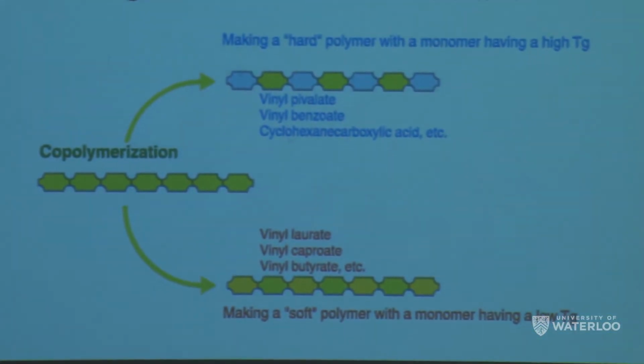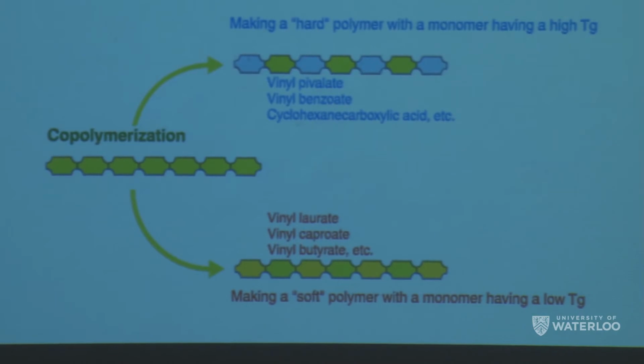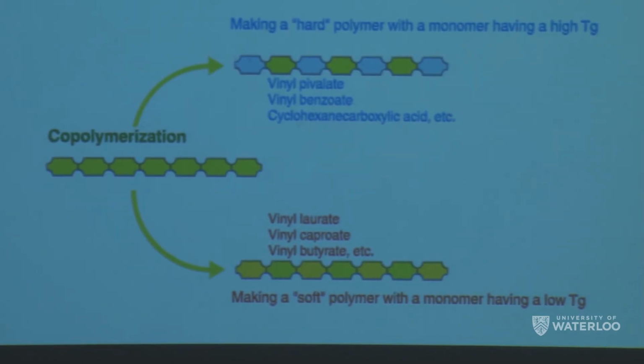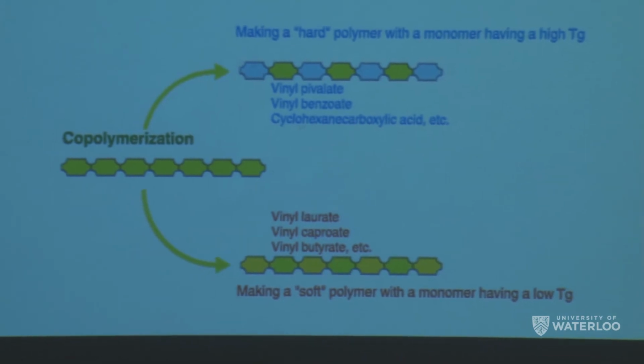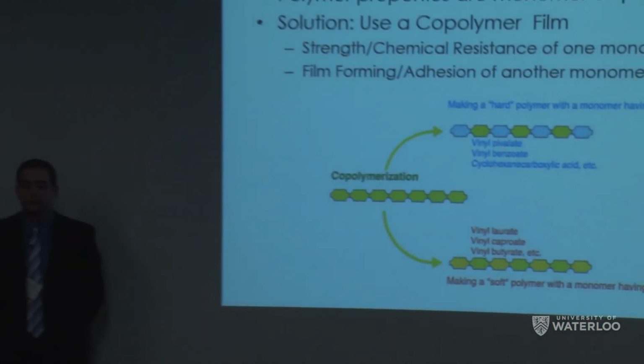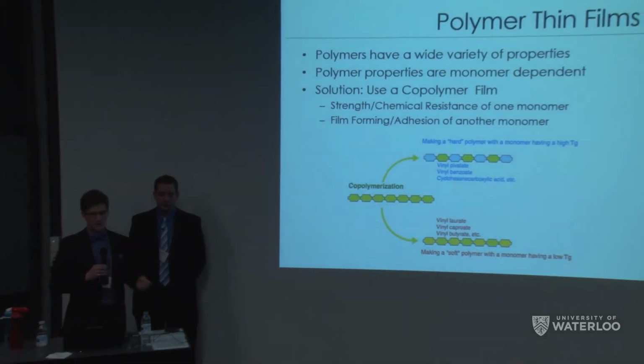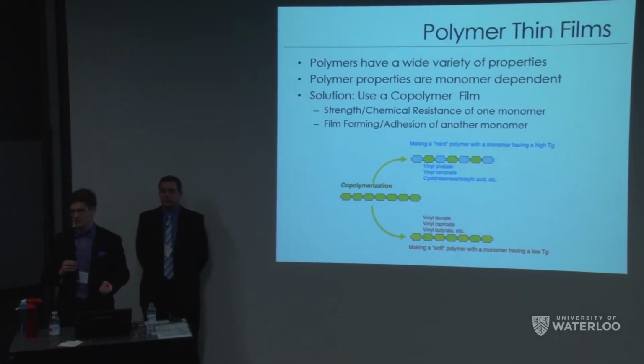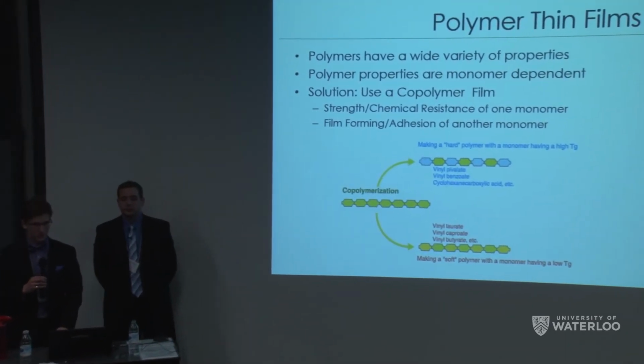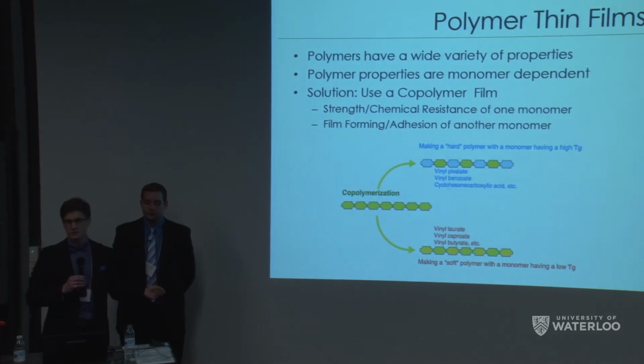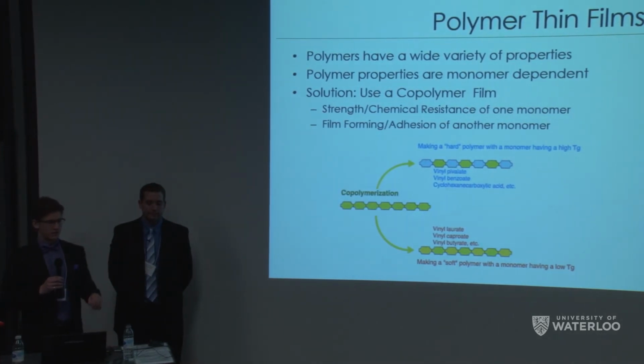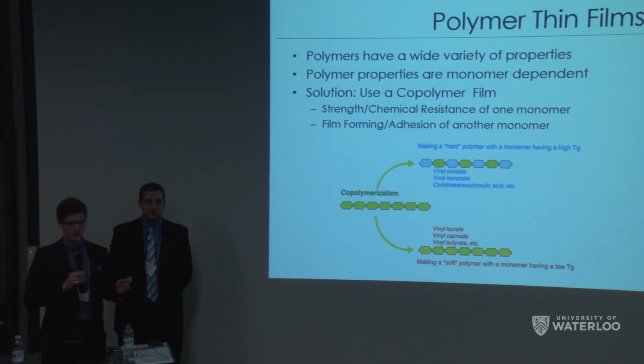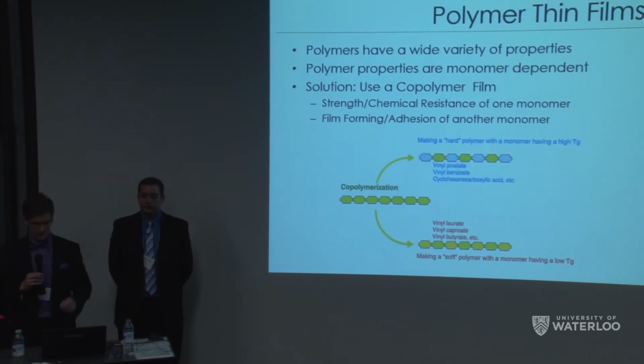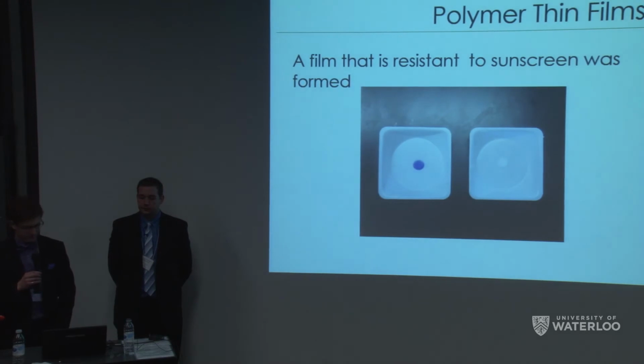The top one has a high glass transition temperature, meaning that it's more brittle, but it's a more chemically resistant film. Whereas the polymer with the lower glass transition temperature is more adhesive, it's more rubbery, but it's more likely to be wiped off by a solvent, such as sunscreen. So to design around this, we've created a copolymer film with a glass transition of about 50 degrees Celsius. So this means that we have the strength and chemical resistance of a high glass transition temperature polymer with the adhesive properties of one that is lower. And here's what it looks like.